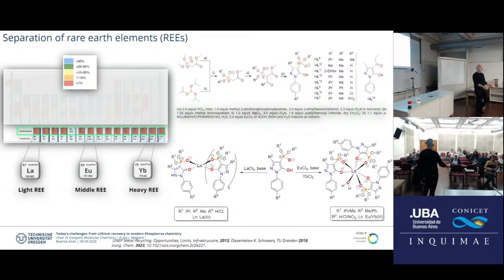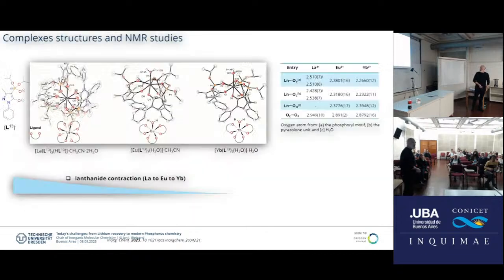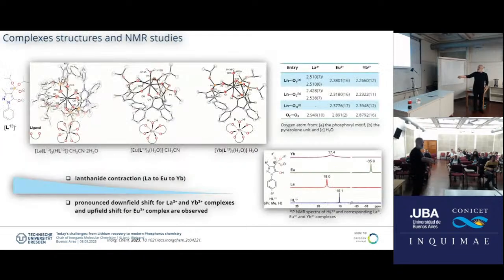And then of course you can look into coordination chemistry. It is not only interesting from the point of view of the coordination, but you can also have a look at selectivity. What kind of coordination is it? With 4 or 3 ligands, can you add a co-ligand, and so on. It's very nice coordination chemistry to look into. Depending really on the ionic radius, we can now differentiate. And also, since we have phosphorus in there, we have a very nice NMR handle, and we can follow the coordination in solution.